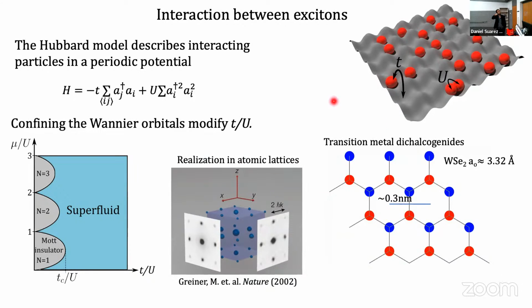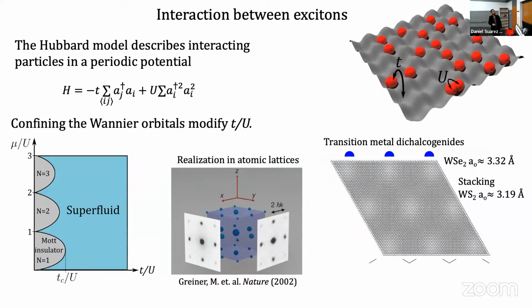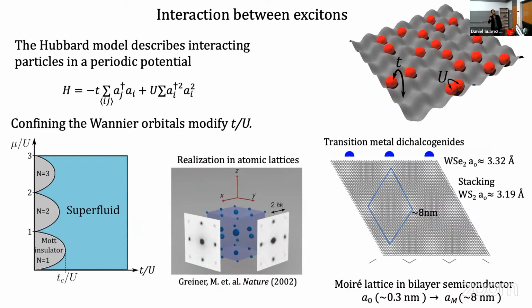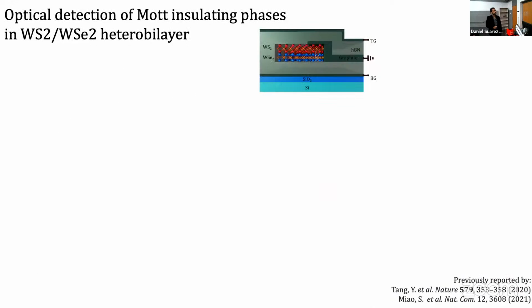The way in which this was manipulated in that material is by changing the properties of the crystalline structure by stacking together similar materials in terms of crystalline structure, but with a slight mismatch. This is going to be reflected in a moiré pattern that then changes the properties of the confinement of the particles. So we can pass from a lattice constant of units of angstroms, 3 angstroms for tungsten diselenide, for example, and when stacking together a monolayer of tungsten disulfide, one can achieve this 4% mismatch that will create a much larger pattern in which the distance between the unit cells is no longer in angstroms, but in nanometers. So we can pass from 0.3 nanometers to 8 nanometers. And this was harnessed to demonstrate the mentioned effect.